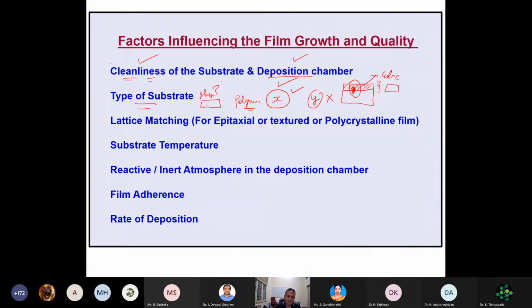Likewise, the substrate type will also tell you the maximum limit for the substrate temperature during deposition. That is also very important. By keeping a polymeric sheet, I cannot go more than a maximum of 140 degrees centigrade. If I go more than 140 degrees centigrade, my polymer will melt and evaporate, and it will contaminate your chamber. So in the case of polymeric materials, mostly people don't give a substrate temperature, or they keep it very low, like 75 to 100 degrees centigrade. If it is glass, we can go up to something like 400 degrees centigrade, depending upon the substrate. If it is quartz, we can conveniently go up to 800 to 900 degrees centigrade.